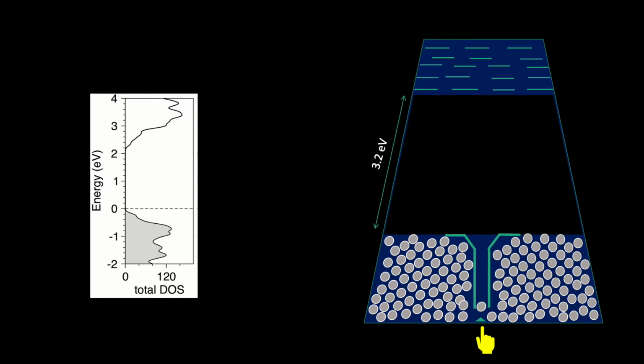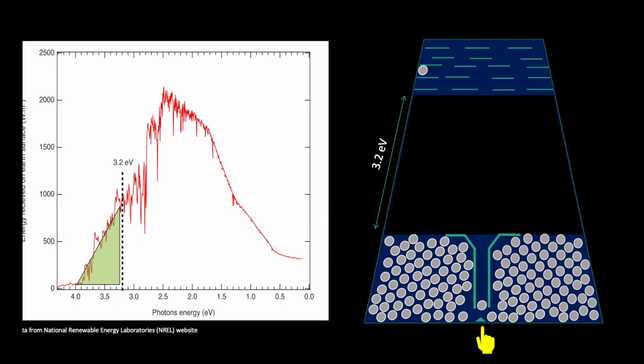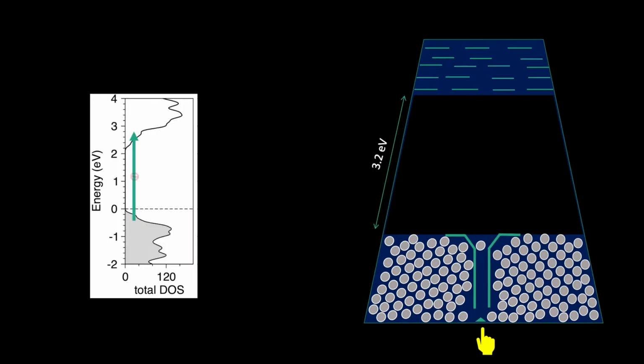As a rule of this game, no ball can exist in the energy barrier and they can just pass it if we flick them with enough energy. In reality, this 3.2 eV energy gap limits the photocatalytic activity of titanium dioxide to just less than 10% of the solar energy received on Earth. This is like, most of the time we are just poking the balls without enough energy.